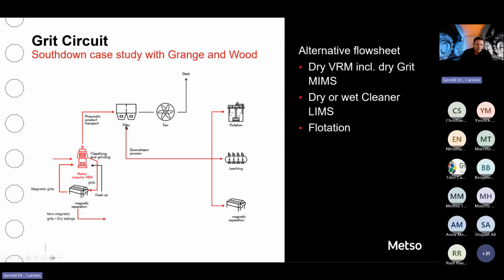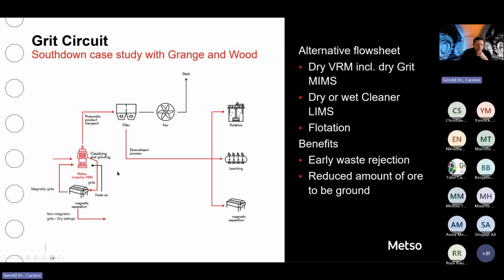At the same time, the main idea is to produce a product for dry magnetic separation and flotation, but surely we want to reduce the amount that has to be ground. And by that process, we have an early waste rejection. We have a reduced amount of ore to be ground, because you can imagine all the siliceous fraction that we take out is increasing the capacity, it's reducing grinding media consumption, and also lowering the energy. And we just lately received the patent for this process, and therefore, yeah, we really think it has a lot